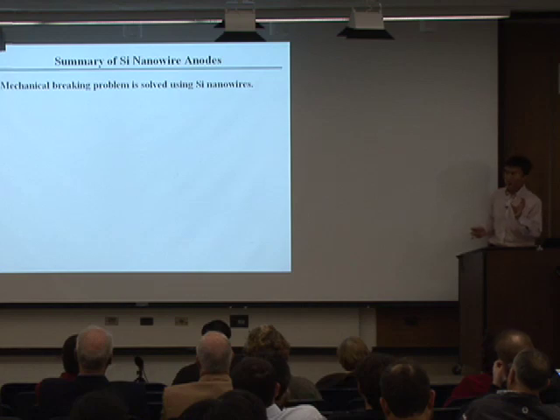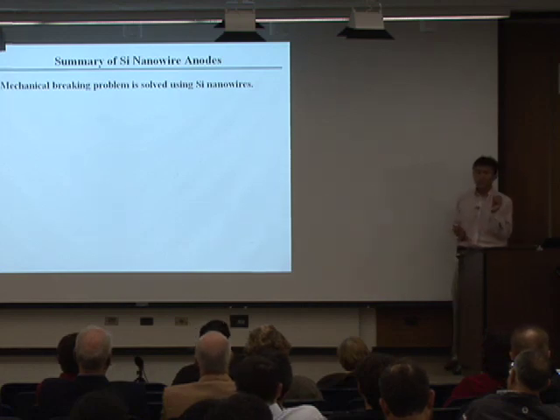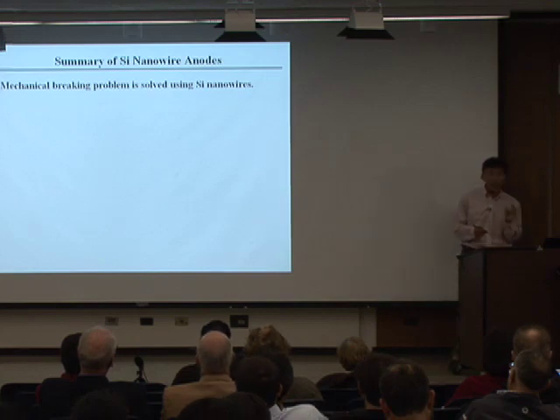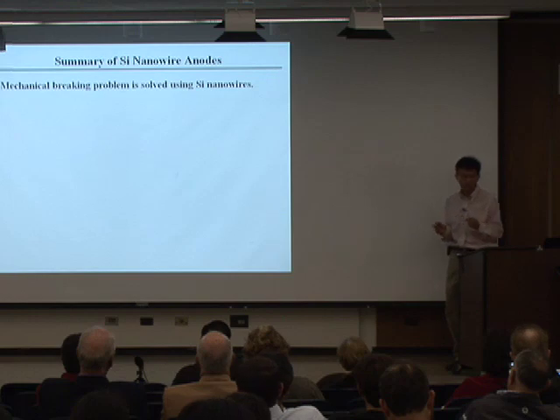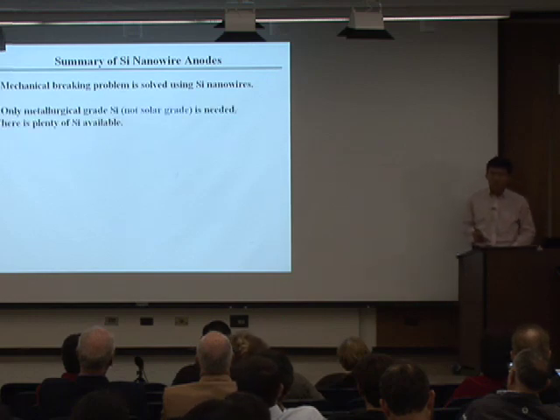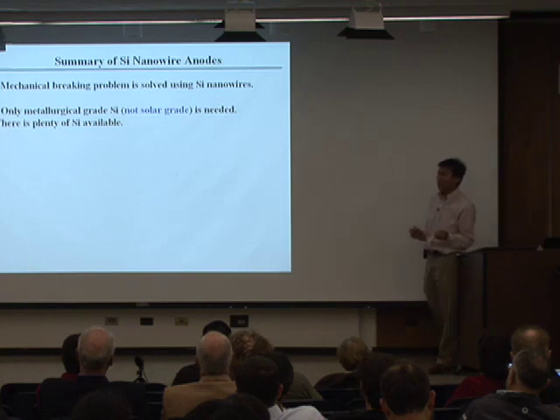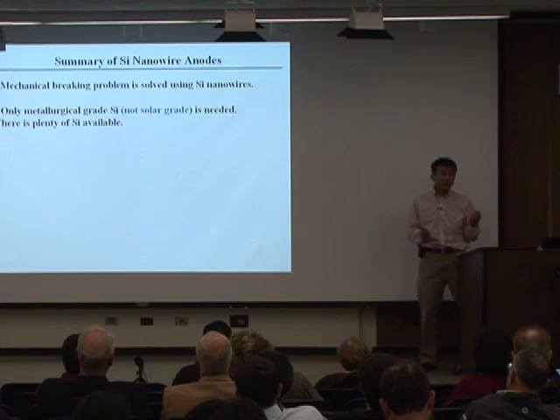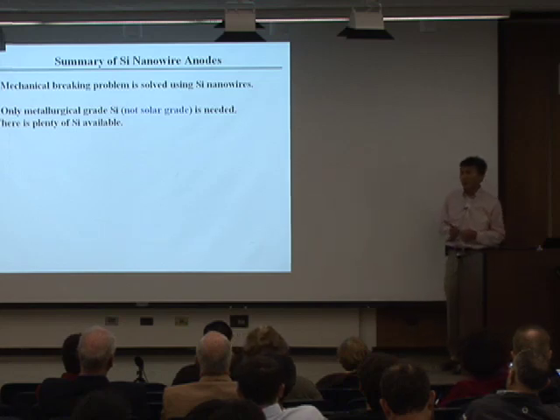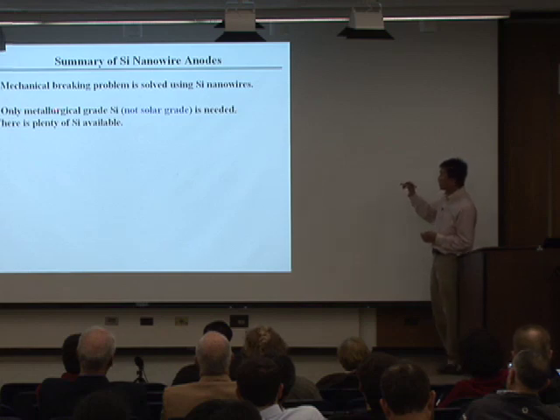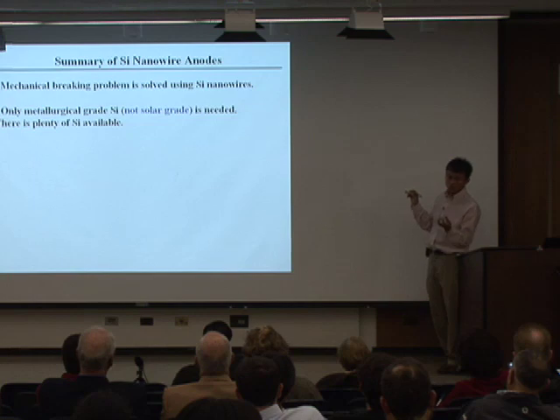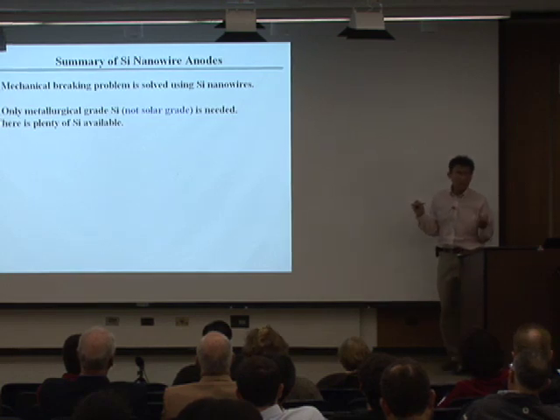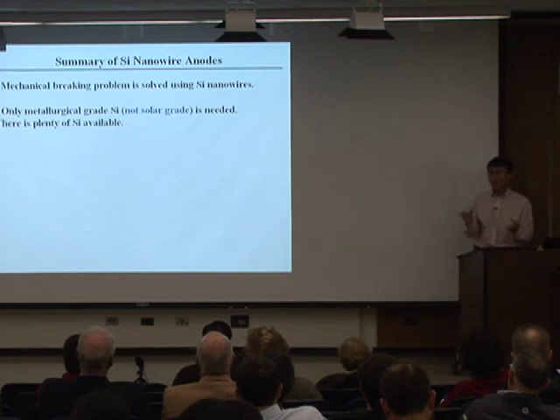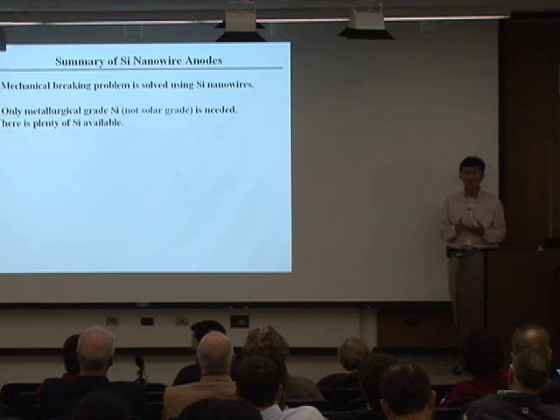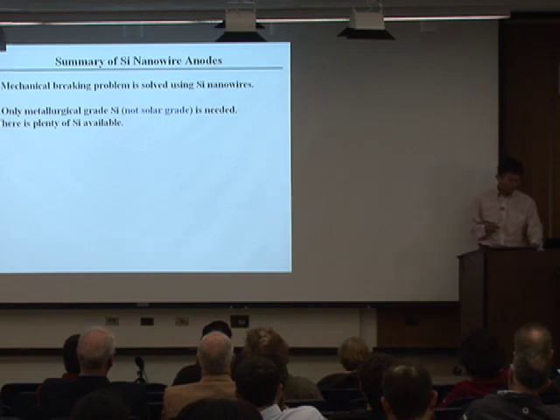Let me summarize a little bit of research related to silicon. So we briefly solved the biggest problem, the mechanical breaking problem, by using nanowire structures. Let me also emphasize the importance of silicon. Silicon is so abundant, so anything you can do on silicon will be great. But everyone will be asking, well, there's not enough silicon in the world, but those are referring to solar-grade silicon, high-purity silicon. And for batteries, you don't really need high purity. Metallurgical grade is good enough. It's maybe $100 per ton, so it's extremely cheap.